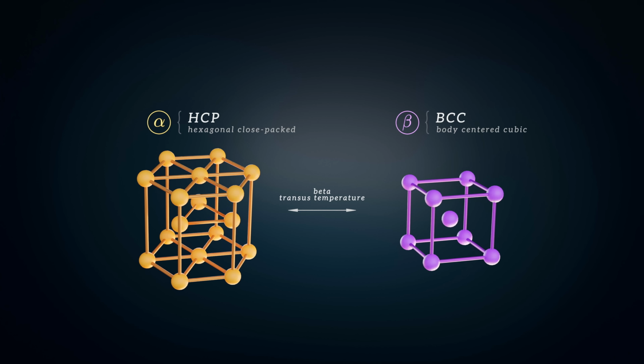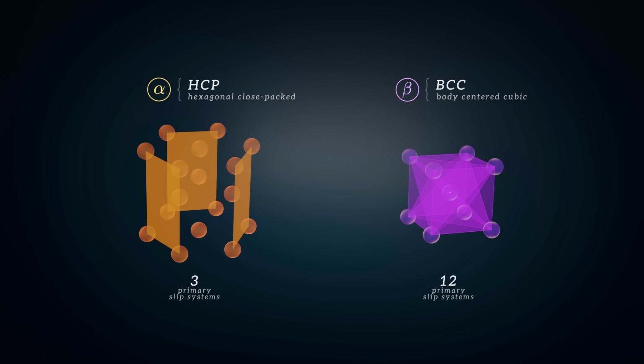The HCP alpha phase has fewer easily activated slip systems, specific planes and directions along which defects in the crystal lattice can easily move. This means the alpha phase tends to be stronger and stiffer, but less ductile than the beta phase. Its closer packed structure also makes it more difficult for atoms to move through the lattice, making the alpha phase more resistant to time-dependent deformation like creep, and better able to maintain its structure at high temperatures.